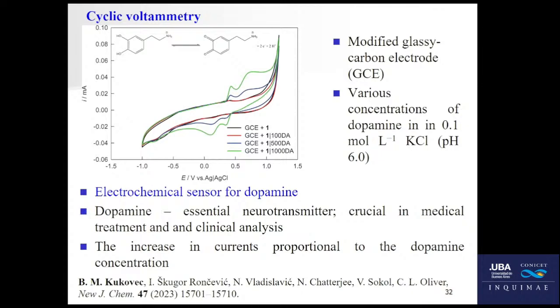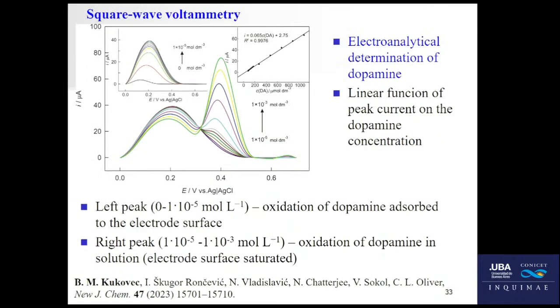So, judging by these results, it seems that our compound described here can be used as an electrochemical sensor for dopamine. However, cyclic voltammetry was not good enough to determine the exact analytical method for the determination of dopamine. So that's why we used square wave voltammetry, which was more efficient for this purpose. In this case, we managed to electroanalytically determine dopamine. And so how it worked.